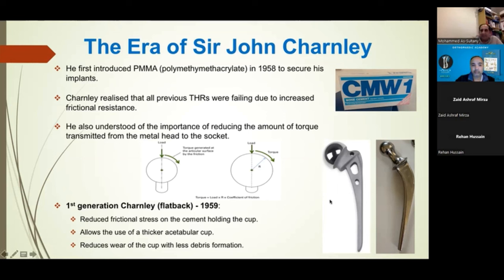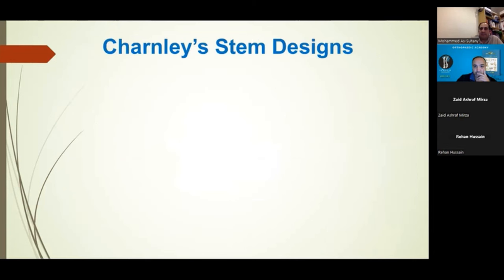So the first flatback was born in 1959, and you can see that the smaller head will mean that you've got a bigger amount of acetabular cup thickness, some more material, so it lasts longer, because obviously it would take longer to wear out the material. And this would therefore reduce the amount of debris formation. So Charnley's first stem was born in 1959, so it was the first generation.